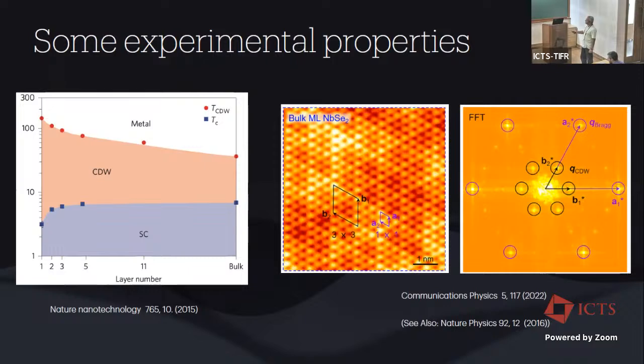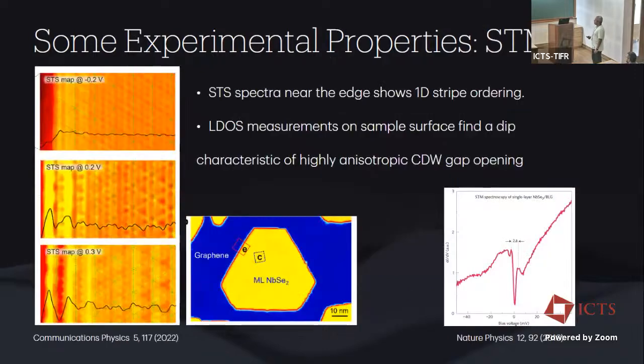So this is your CDW state, and if you Fourier transform it, you can see the Bragg peaks that are generated by the CDW state ordering out here in addition to the structural Bragg peaks. And effectively what it means is that the CDW state itself is not breaking the lattice symmetry that you're dealing with for this problem, right? But then there are certain interesting features that come out. For example, something which is not seen in bulk NbSe2, although you have a 3Q CDW phase, is that if you look at the edges of this material, and if you were to do a scanning tunneling microscopy experiment from the edge towards the bulk, near the edge it forms these stripe-like patterns.